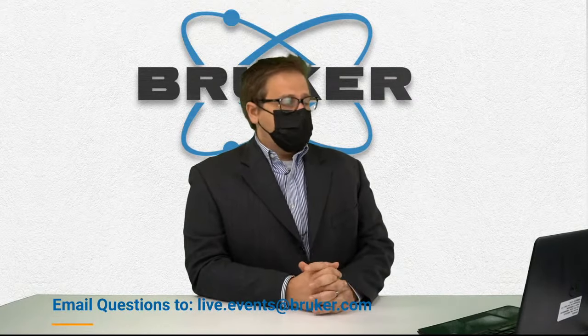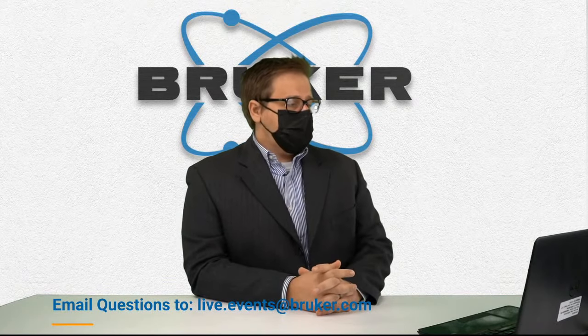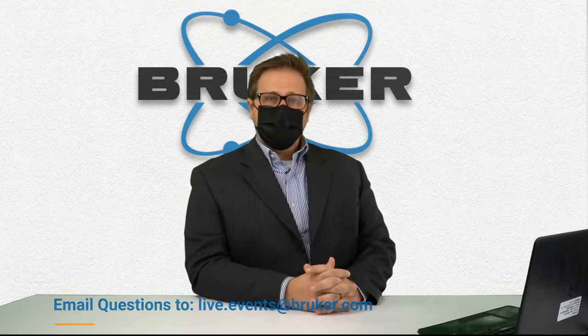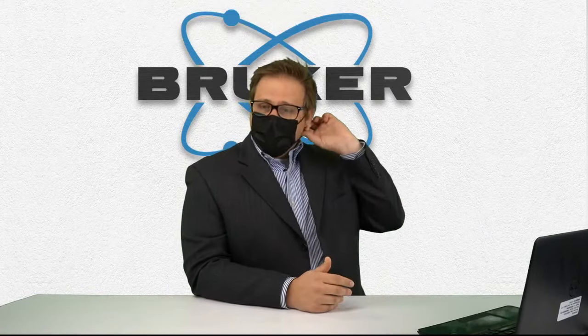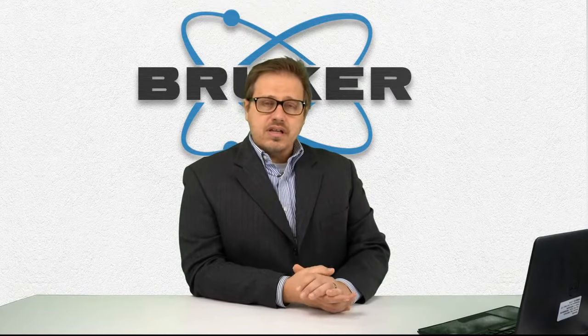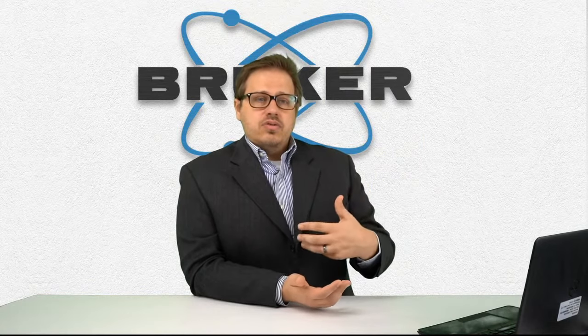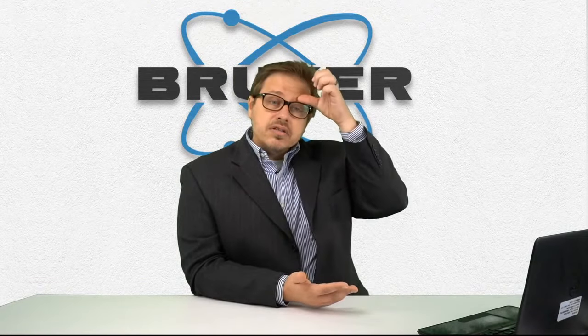So the first question is from Andrea, and that is PDF and SAXS in relation to the 2D detector. So I think probably the question is, can it be used, and is it useful? The answer to that would be it can be used for both PDF and SAXS. So a detector like the Eiger uses a silicon sensor, so it can be used for things like moly. And because it has such a large open active area, you actually gain back any losses that you lose due to, say, transmission of the beam through the sensor. One other thing to note is that the Eiger is compatible with those radiations, so you don't have to worry about radiation damage with it.